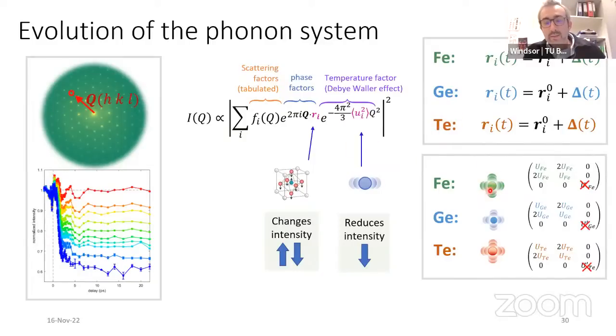And the incoherent oscillations of every ion species would also be described analytically. And in this case, we would need a tensor. But lucky for us, there are all sorts of symmetry restrictions on these terms here. First of all, this is a symmetric matrix, so we only have 6 terms. And then because of the specific positions in the unit cell, we end up that every single ion can be described by one term, this UFE here. So it's just one term that is time dependent and comes into this matrix. And the same is actually the case for germanium and for tellurium, which is very convenient for us.